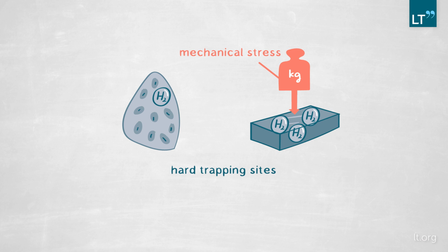However, it may happen that hydrogen doesn't like to stay in a particular lattice, and it will wander around in the form of movable or diffusible hydrogen. So many studies dealing with materials design consider hard trapping sites, because if we can capture hydrogen in there, it doesn't have any more freedom to move around and cause trouble. We can test the properties of a material with hard trapping sites by ex situ experiments. This means first we charge or load the material with hydrogen, and afterwards we do the mechanical testing.